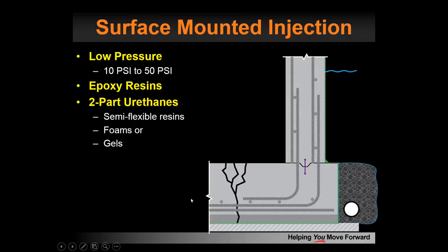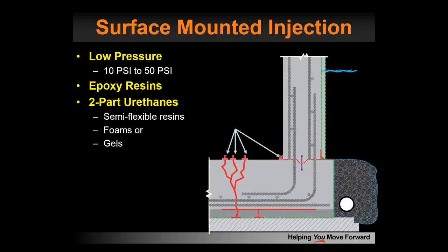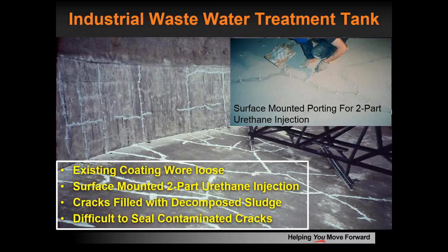And sometimes we have shadows, little voids that run behind the steel or under the steel where water can migrate as well. So let's look at the surface-mounted injection. Typically, it's a low-pressure technique where we put ports on the surface, and we either use epoxy or a two-part urethane, and we push that grout back through the crack and try and make the concrete monolithic. Here's an example of that. This is an industrial wastewater treatment tank where we did surface-mounted ports, and then we pumped a two-part urethane injection grout in all of the cracks to create a seal.